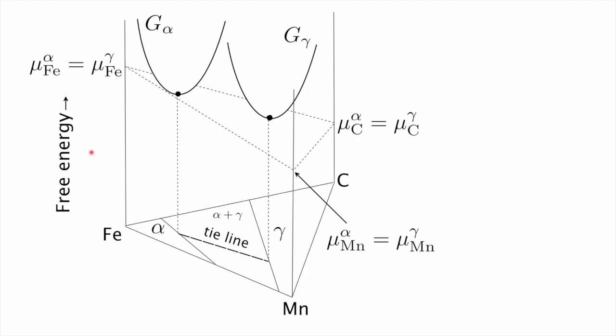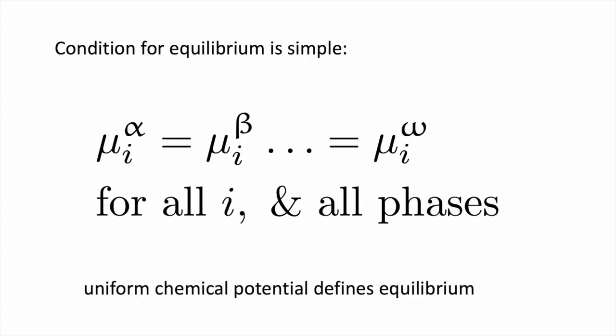And that applies even for a ternary system where we have three elements, that is, these free energy curves are actually free energy surfaces in three dimensions, and we draw a common tangent plane here, and where it touches those surfaces gives us the equilibrium compositions of alpha and gamma at the temperature of interest. But I said to you that I don't want to draw diagrams anymore, because it will get impossibly complicated as we go to more than three elements. All we need is for the chemical potentials of each and every element to be identical in each and every phase. And we can do this if we have thermodynamic data. We can simply calculate the point where these chemical potentials are identical.